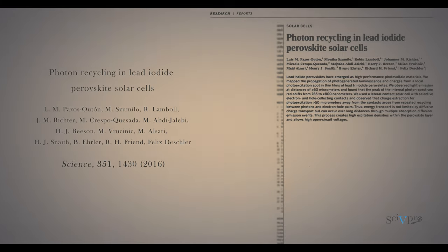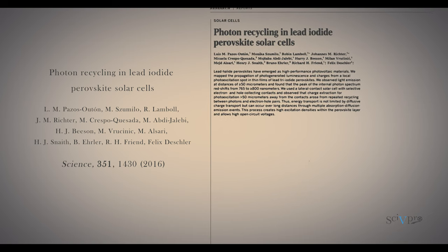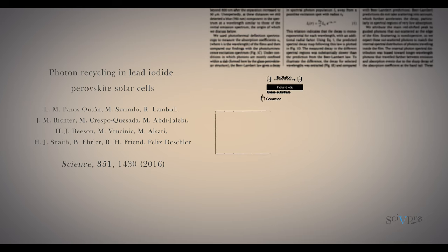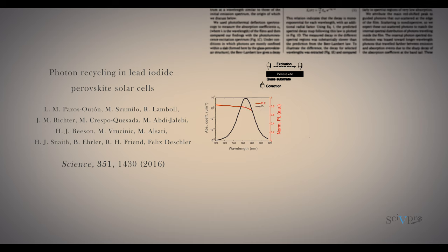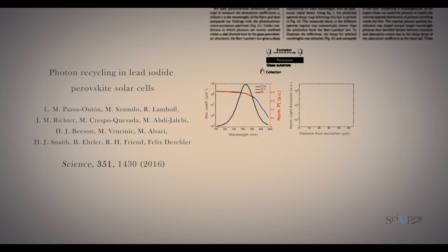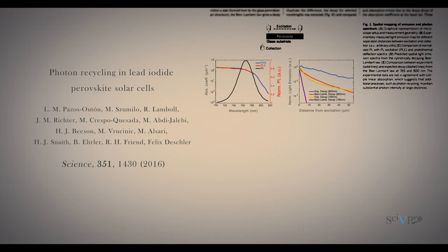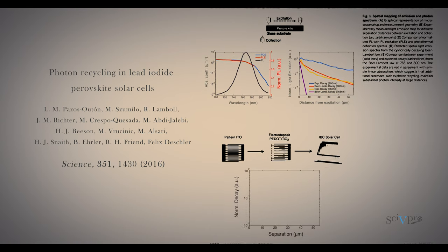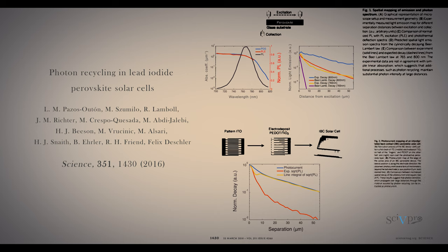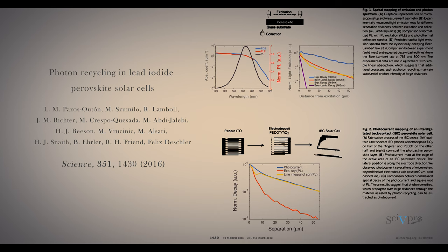And by this sequence of processes, you get this photon recycling effect. And when we tried to see this together in our paper, we used photoluminescence microscopy to look at the transport of charges and photons in the material. And we found that the transport occurs at length scales which are much beyond the expected length scales from just absorption. And we were really excited to see that and concluded that photon recycling has to happen in this case.